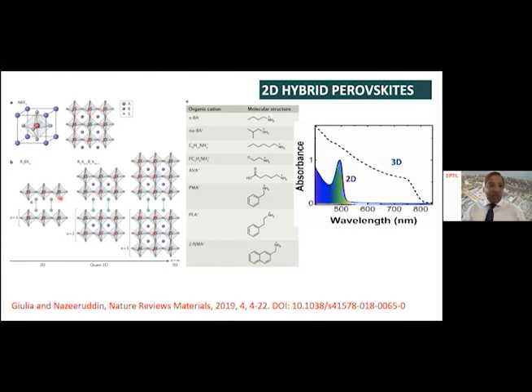So this is an n equals 1 low-dimensional perovskite. This is also a low-dimensional perovskite, but two layers are joined together. This is named n equals 2. That's two layers joined together, with a big organic cation slicing this perovskite. And the third example I'm showing here, just to understand what these bigger cations are doing. If we change the ratio between the smaller cation and the bigger cation, you can see n equals 3. This way you can control the number of layers.